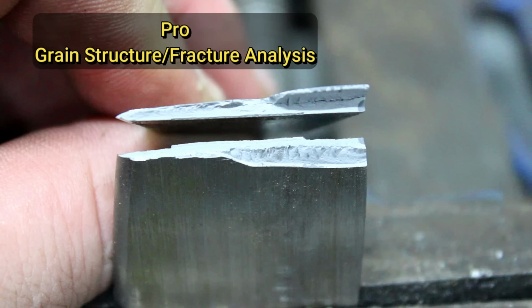Now, on the pro side of the heat treatment, I'm still dialing in the kiln. There's not a lot to it. You identify the steel, reference your temps, and for 52100, we're in that 1500 to 1550 range. And from there, it's about soak time, holding at temperature long enough to get full austenization. So when you come out of the kiln and into the quench, you get a complete martensite transformation. Based on the grain structure, that part is working. We're seeing a fine, uniform structure with no grain growth, which tells us the austenization temps and quench are in the right range. Where things are breaking down is in the tang.